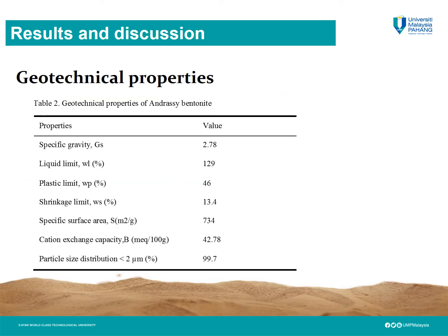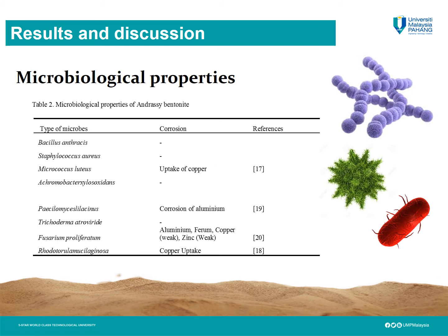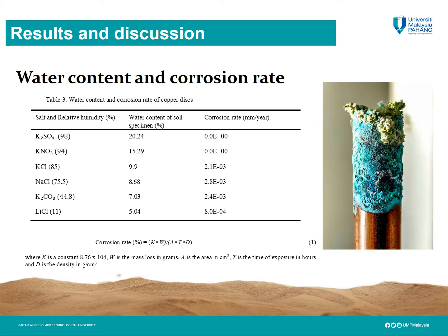These are the geotechnical properties of the bentonite used in this study. Then we identified the microbiological properties. Based on this, we identified a total of 8 types of microbes present in this specimen. As for the effect of water content on corrosion rate, we identified that higher water content does not necessarily influence the corrosion rate.